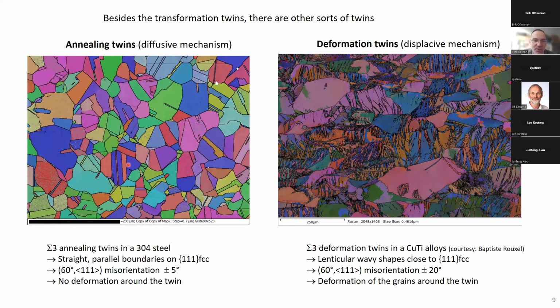And here it's an EBSD map, an electron backscatter map. If you measure the misorientation between these two grains, it's 60 degrees around this orientation. And there is another kind of twins that are deformation twins. I will insist more on these deformation twins because they also result from a displacive mechanism. They are really similar to martensite, actually. And you see the difference here? Here we have straight boundaries, and here it's not straight. It's curved, it's lenticular shape. It looks like martensite, but they are twins.